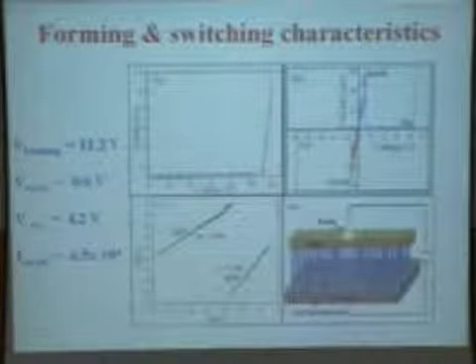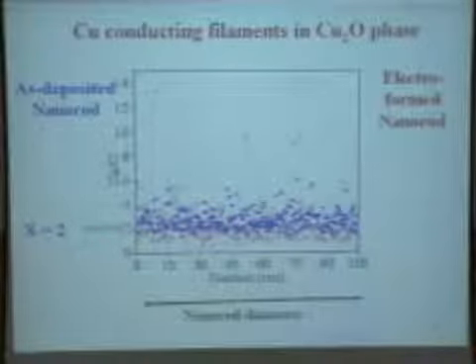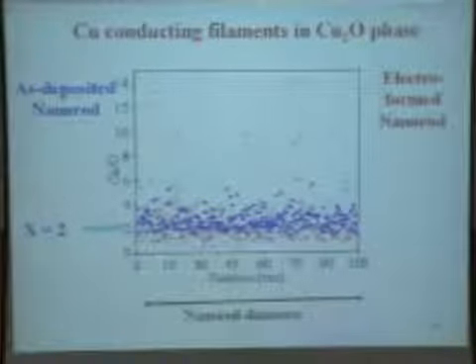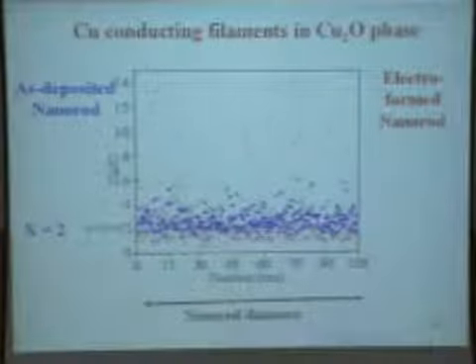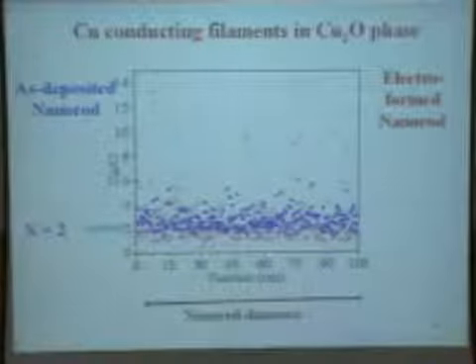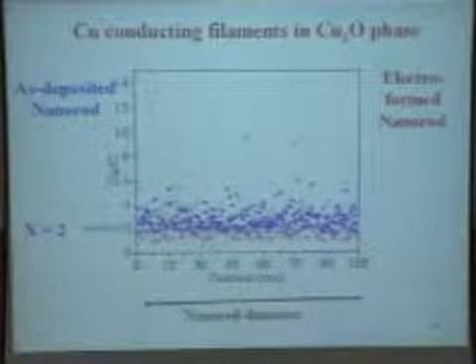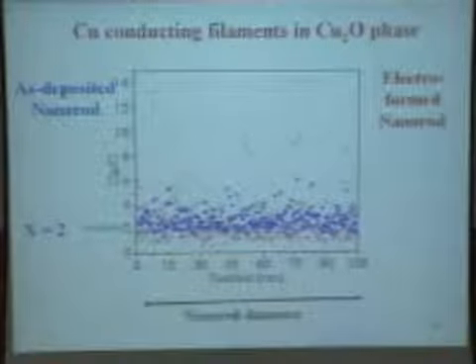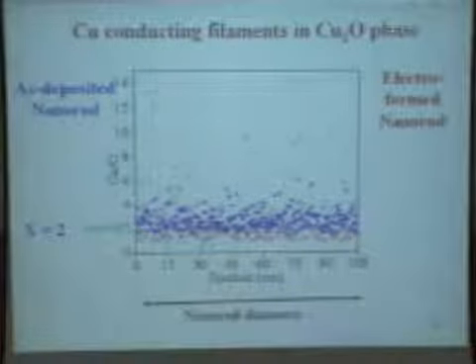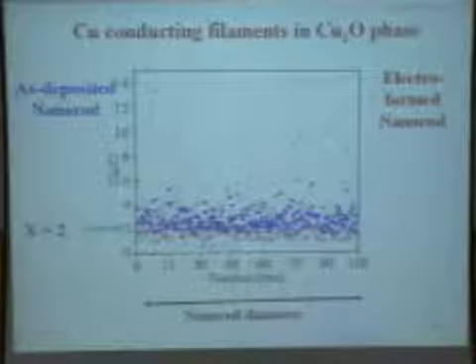Using copper oxide, not a copper oxide thin film but copper oxide nanorods, it was possible. We measured the composition of one copper oxide nanorod before forming and after forming, the concentration of copper with respect to oxygen. You can see that in the electroformed nanorod, the copper concentration at certain points becomes very high. That indicates that within that 100 nanometer dimension, at certain points, there is some formation of a copper filament.